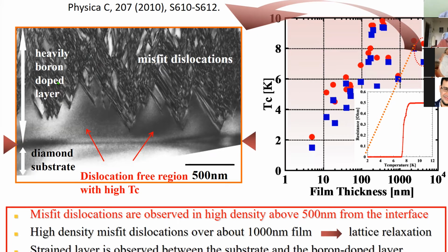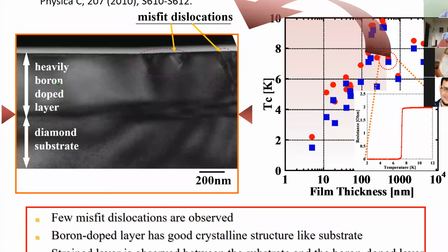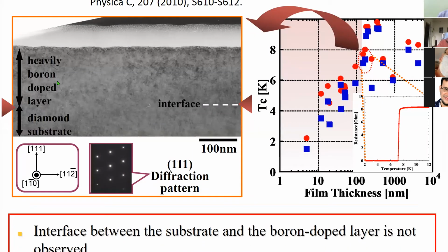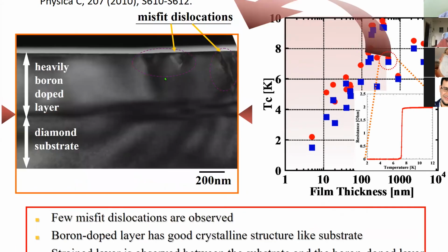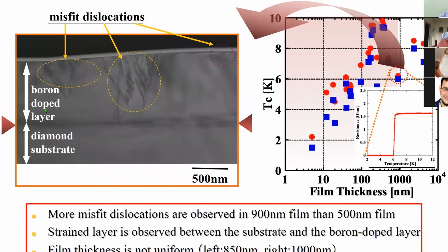So just a quick overview of what's happening in the thickness measurement, and the thickness difference of our material. This is a cross-sectional TEM, and the TEM specimens aren't so good in this case, but it's relatively homogeneous, and we get defects a little bit far from the interface. Finally, for a thicker, relatively thick film like 900 nanometers, you can see the dislocations start, not from the interface, but mostly in the middle in this case.